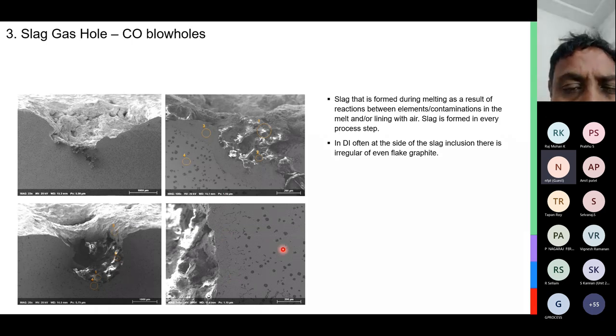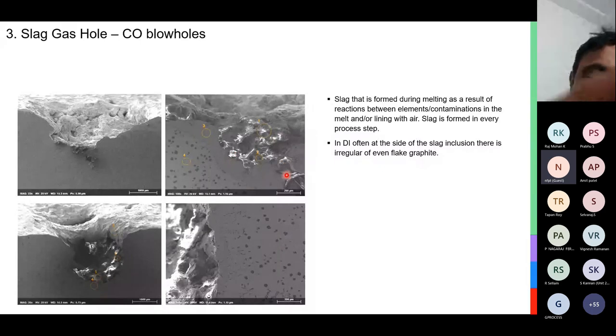So if it's a manganese sulfide slag, then you will have a thin layer of graphite flakes next to the inclusion area. But if it is the other form of slag, which can be magnesium oxide or coming in from the furnace, you would not see so much flake generation next to the inclusion area.